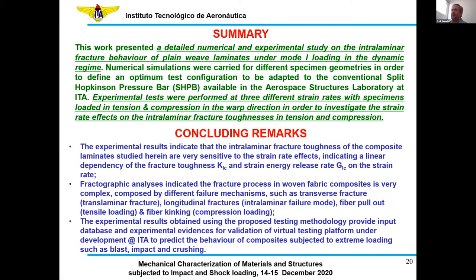Some concluding remarks are indicated here. We have found that experimental results indicate that the intralaminar fracture toughness studied herein is very sensitive to the strain rate effects, indicating a linear dependence of the fracture toughness on the strain rate. Fractography analysis indicated that the fracture process involving these composites is very complex due to the fabric architecture, composed of different failure mechanisms such as transverse fracture, longitudinal fracture, fiber pullout, and fiber kinking.